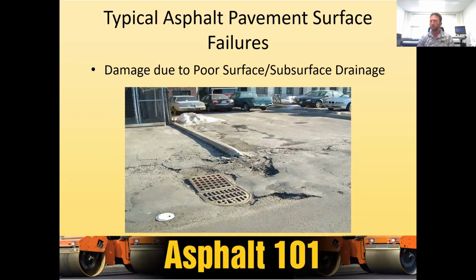All right. So what are some typical asphalt surface failures that we deal with after we construct and while we're maintaining our asphalt pavements? Certainly damage due to poor surface or subsurface drainage. If I've got area drains or inlets within my parking lot or within my roadway, I want to make sure that water's getting to those. Okay. In this case, you've got kind of a curb that's damming some water, and you can see all the damage around that grate inlet right there because the water's not getting into the grate. Okay. So you've got a combination of restricted flow, or the drain is sitting higher than the asphalt around it. So as water ponds around there and it gets driven on, the asphalt starts to fail.